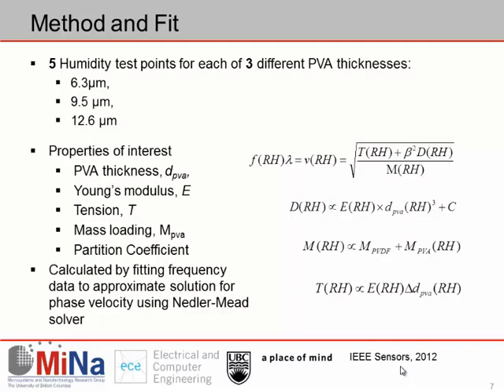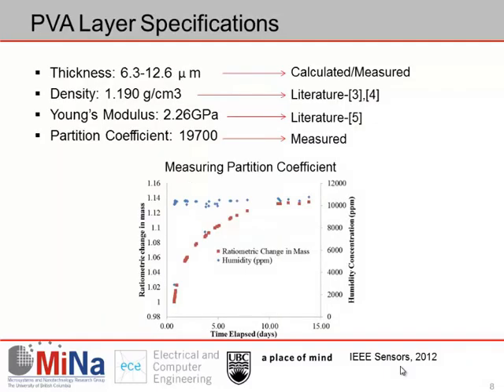So in this case, the solvent is water. We did this by fitting the frequency results to the equation introduced earlier and using a Nelder-Mead solver. So the idea is we had a frequency shift, and we associated that frequency shift with not just mass loading, but also PVA thickness change, tension, and Young's modulus shifts.